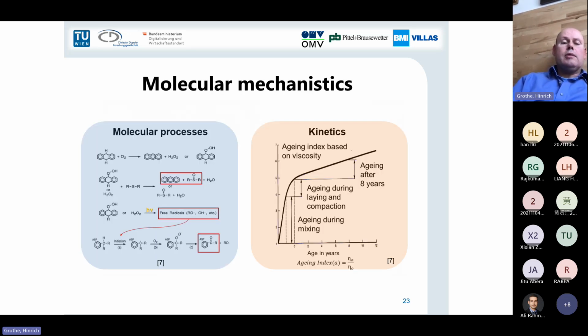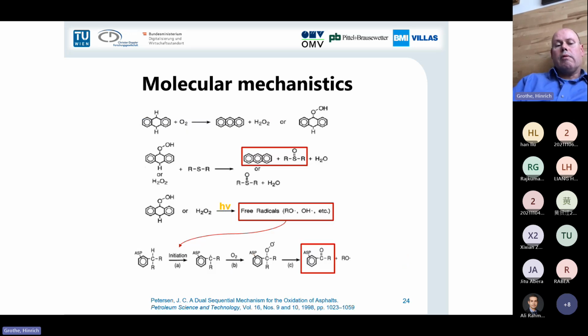Okay, so then let's return to what I said already. We have the short-term aging and we have the long-term aging, and in particular the long-term aging, which goes through the whole lifetime of our road, is very important. And within this, it is the reaction of radicals and light and the oxidation of aliphatic and aromatic compounds.